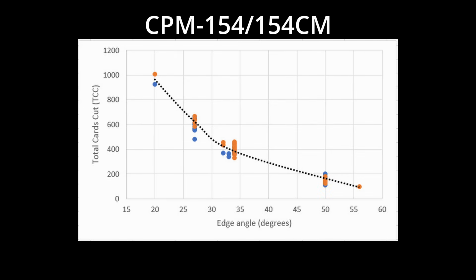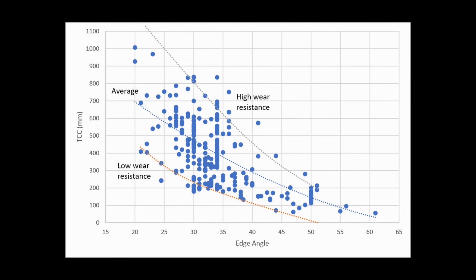The 20 degrees per side edge had more than 5 times the edge retention of 28 degrees per side. A steel with average wear resistance can outcut a so-called super steel with high wear resistance if the edge angle is dropped by only a few degrees per side.